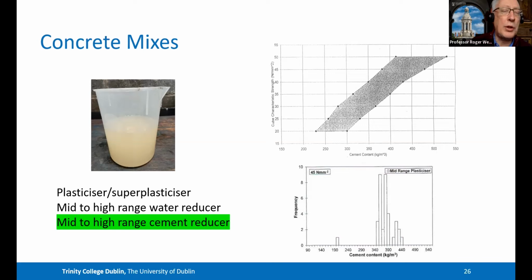So it's quite interesting, the terminology that we use, because we tend not to call them plasticizers anymore, the things that allow us to reduce the water content, because it gives us the workability that we need. And a lot of water is added simply for workability purposes. It's not there for strength purposes. It's there to make the concrete workable. And if you use a plasticizer that makes the concrete more workable, you can use less water. But if you're happy with your strength and you have some flexibility, you could also use less cement. So the use of a plasticizer means that we can use less cement. And that's very commonly practiced, and we should recognize that. Most concretes use a plasticizer or a superplasticizer, but we don't do ourselves a service by calling it a mid to high range water reducer, because if you're also reducing the cement content, why not call it a mid to high range cement reducer? Because it enables us to reduce the quantity of cement and still get the same strength and the same performance. So there's a thought.